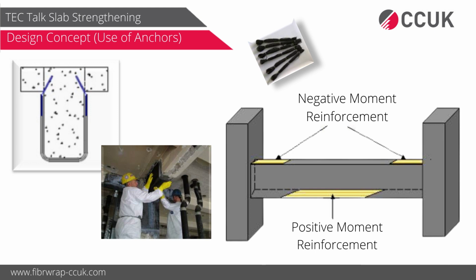But there is another key construction detail which many people miss out, especially for hogging moment strengthening. Whenever they are doing hogging moment strengthening, they apply FRP on top of the slab or the beam and take it up to the ends of that span and then stop it there, because there will be a column in the way or a wall there or something. The reason is that you cannot continue FRP beyond that point. But in reality, that's the point where we are going to have the peak stresses. So if we are stopping or curtailing the reinforcement at the location of the peak stress, technically there is no point in doing that strengthening, because that's the location where we need the strengthening the most, and it will not be effective at that location.